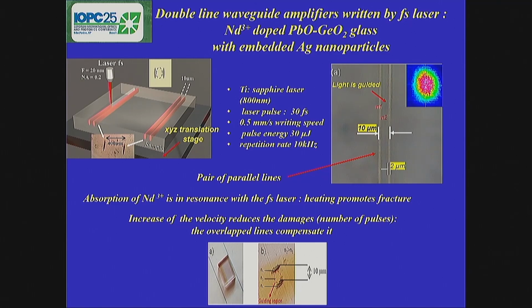In this case, we used a composition based on germanium dioxide because we based it on previous results in which interesting results about optical amplification at the third communication window were obtained at about 1.5 micrometers, doping the material with ytterbium and erbium ions. But these results refer to the use of neodymium. And we had a problem here because neodymium absorbs at about 800 nanometers, which is in resonance with the operation of the laser we use for the femtosecond irradiation. So the sample heated, it fractured, and we had to look for a solution.